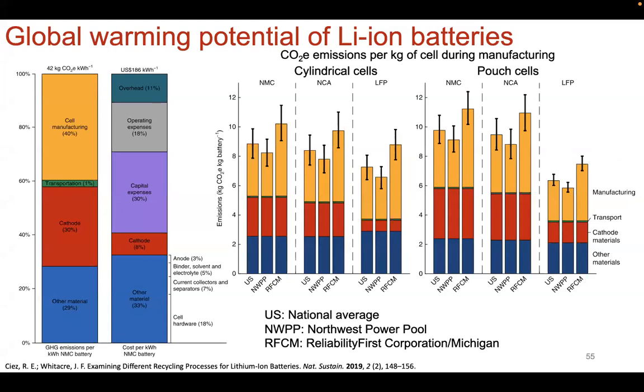Yes, there's a tinge of that, but when it comes to sustainability, one does have to think about the geometry in which the cell configuration is going to be. So here you see a comparison from 3 different sources: national average, this group called the Northwest Power Pool, and then another corporation in Michigan, in terms of tabulating how much CO2 equivalent is produced. And what you see is the emissions for these 3 sources will vary, but for cylindrical cells versus pouch cells, you see that pouch cells have an advantage for decreasing the amount of CO2 equivalent when it comes to lithium iron phosphate chemistry.